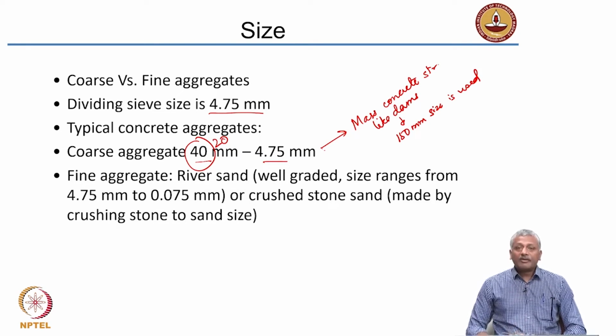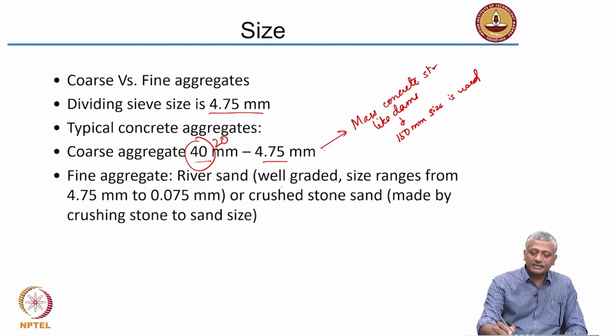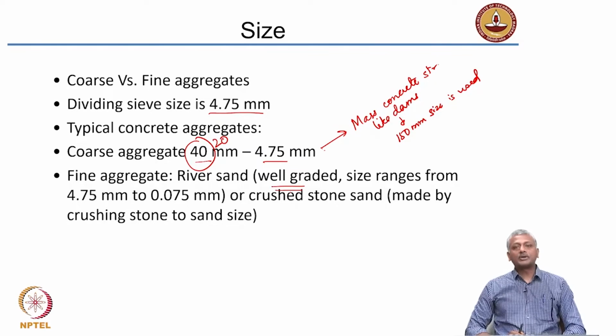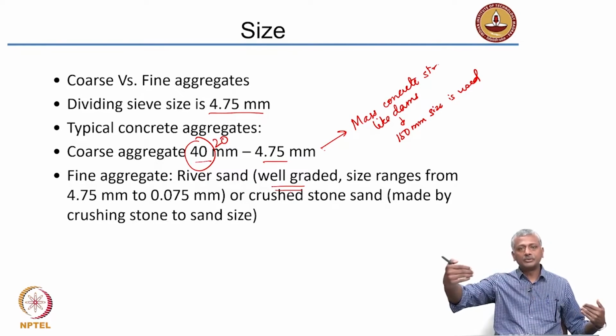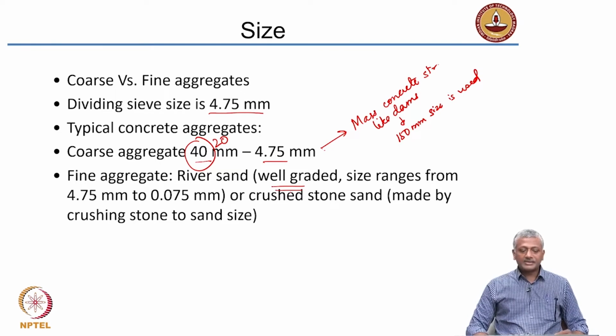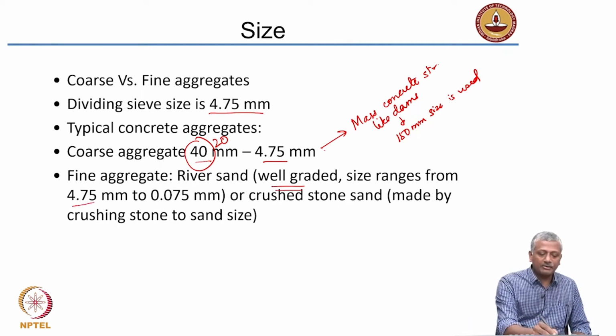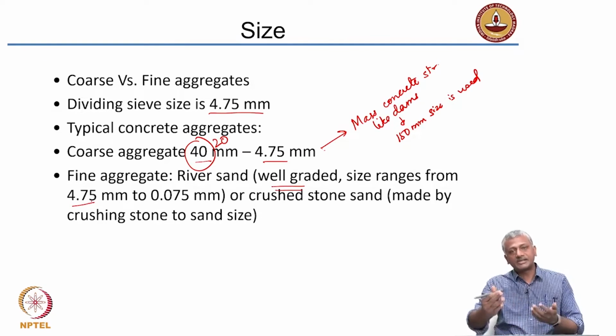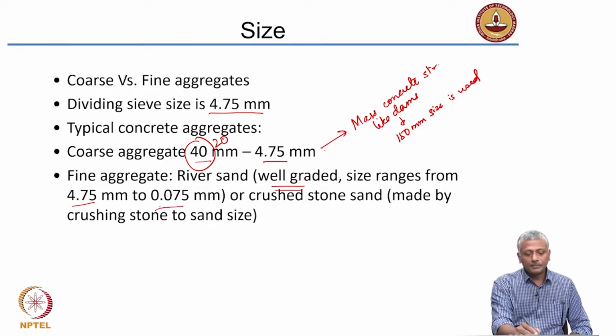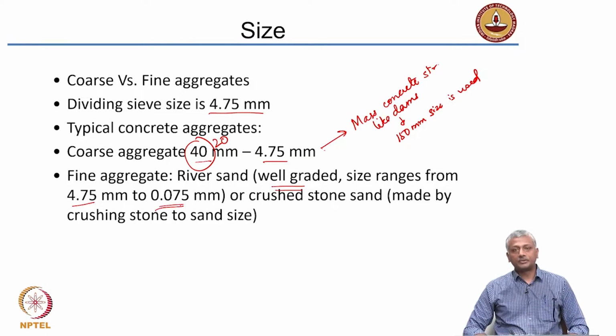Fine aggregate, on the other hand, as I said, the most commonly used fine aggregate around the world is river sand. River sand is generally well graded, that means it has a range of sizes from very fine to the coarse size. The size ranges typically that you see in sand are from 4.75 millimeter, which is the upper limit of sand, to 75 micrometer or 0.075 millimeter. The smaller size particles can create some problems later in the concrete, I will talk about that later.